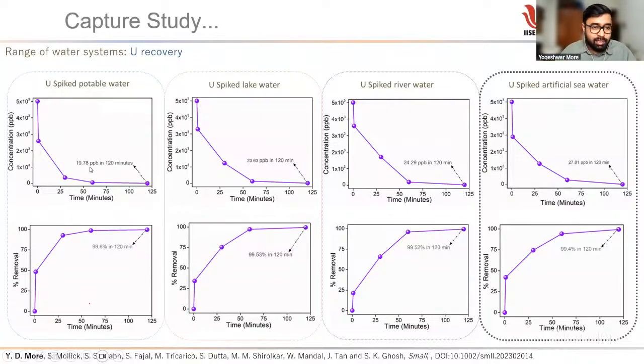So what we found is that in uranium spiked potable water the kinetics is very high. We are capturing almost 99.6% in 120 minutes. Similarly, in uranium spiked lake water, we are able to get 99.53% in 120 minutes, and in uranium spiked river water we are able to extract nearly 99.52% in 120 minutes. So for all three samples, the percentage is nearly 99.5.